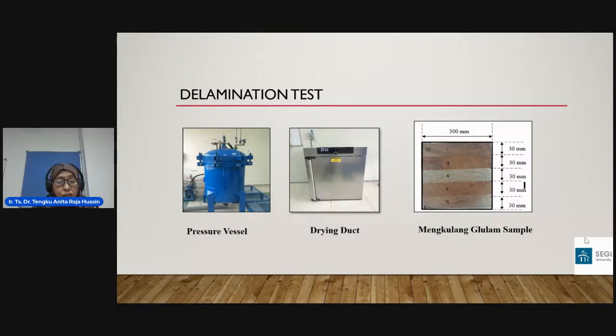The second one is the drying duct. The drying duct was to dry the specimen for a period of 21 hours to 22 hours in air at 60 degrees to 70 degrees, with relative humidity equal to 15% or less, circulating at a velocity of 2 meter per second to 3 meter per second. And the last picture here is the Mengkulang Glulam sample.